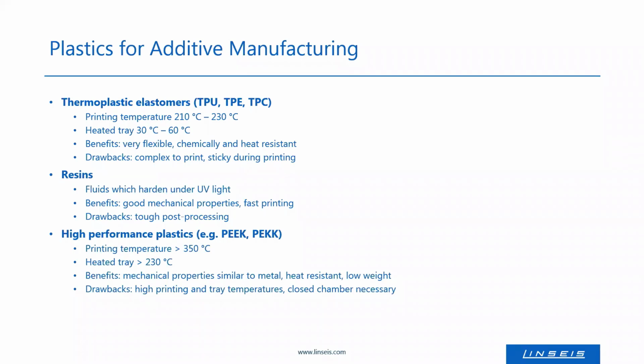And also there are some high performance plastics which are used in additive manufacturing, but here the printing temperature is really high, so above 350 degrees Celsius, and the heated tray must also be at a high temperature. But the big advantage of these high performance plastics is that the mechanical properties are really similar to metal, and they are really heat resistant and show a lower weight compared to metals. And the disadvantage, as already mentioned, is the high printing temperature and the heated tray. And furthermore, a closed chamber is also needed, because here then the temperature is more stable.